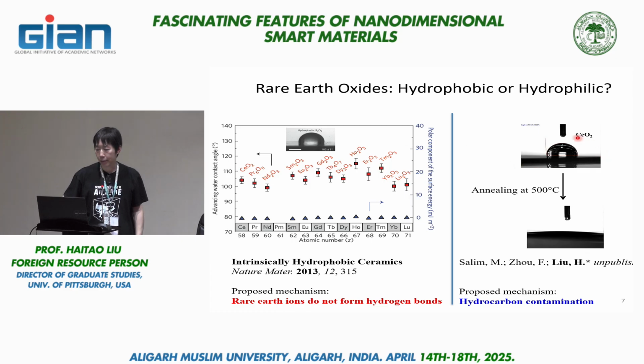We repeat the experiment, making cerium oxide thin film, and that indeed is hydrophobic, just as they reported. However, once you anneal the sample in air at high temperature, what we are actually doing here is burning off the surface hydrocarbon, and the films quickly become hydrophilic. So just another example of the same kind of phenomena impacting different kinds of materials.